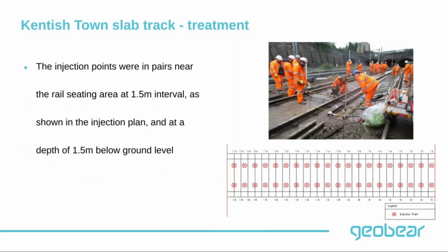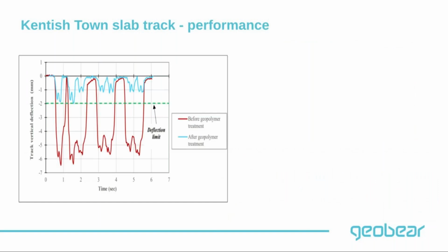What we've done, we've basically been commissioned to come out and carry out our injections underneath the slab to strengthen the ground and fill all the voids between the soil and the slab. And we've done that with what we call the injection grid. So we had an injection interval of 1.5, so injected every 1.5 meters to create the stabilization effect. And as we were injecting, we were carefully monitoring the slab level using laser levels to ensure that we raise the track to the desired geometry.